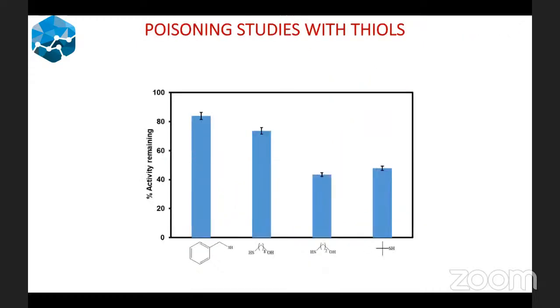So we then did some poisoning studies. Remember what we did was to insert the ruthenium complex inside the MOF. So how do we know that catalysis is taking place inside the pores of the MOF, or is it taking place outside the pores of the MOF?